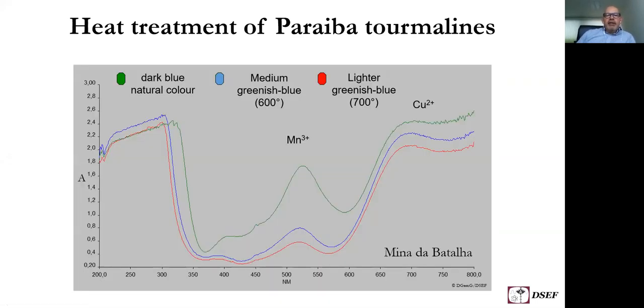This is another example of heat treating a stone. We did that at the very beginning when we first had the stones in the lab from the Paraiba mine, starting with a dark blue color, heating it up here at a temperature of 600 degrees, resulting in a medium greenish blue. We just reduced the manganese 3+, and at even higher temperature, the stone turns lighter but also brighter.